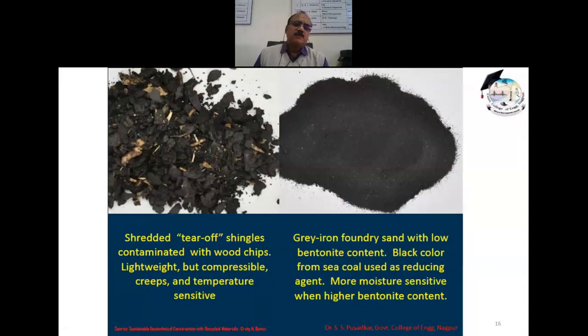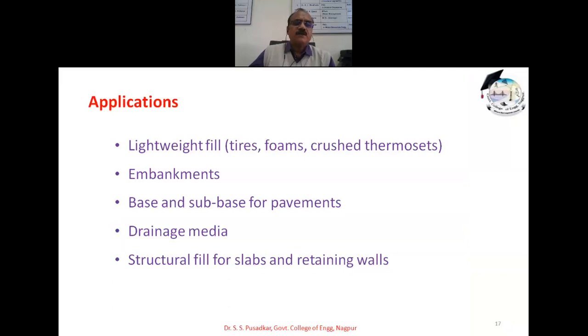Okay. This is another, about the tire. Shredded tear-off shingles contaminated with wood chips are lightweight but compressible, and hence they also creep and are temperature sensitive. So you can use the pieces of your tire in the construction, or you can shred it into small particles, and then you can use that shredded tire as tire chips. Also, you can use the sand which is obtained from the grey iron foundry with low bentonite contents. They are black in color from sea coal used as reducing agents. They are more moisture sensitive with higher bentonite contents, and hence you have to take proper precautions again in utilizing these waste materials. They can be used for lightweight fill such as tire, foams, crushed thermosets, embankments, base and sub-base for pavements, drainage media, structural fill for slabs and retaining walls.